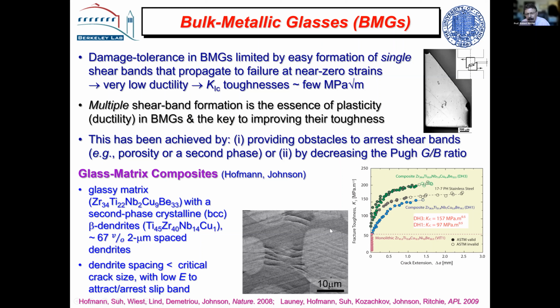This was a while back, but he put a second phase in so that he could basically stop these shear bands from getting long enough so they could cause failure. You want the shear bands because they generate plasticity, but you don't want them to get too long to cause failure. And the result was very high toughness. In the original Nature paper they didn't measure the toughness properly, but we did a little bit later. And you get these great R curves now, and you're getting toughnesses up around 150 megapascal root meters. And these glasses have very good strength. But it's hardly a metallic glass now because it has this crystalline ductile phase in.